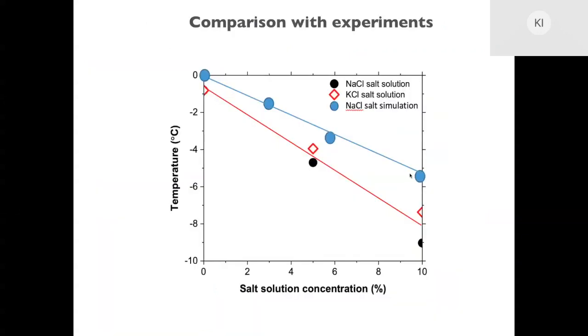The interesting thing here is that from the phase diagram of water, we can go and find the temperature that corresponds to the pressure that we computed on the small scales between the interface of cement and ice, and plot it as a function of the sodium concentration that we have. And here we see that we have a good comparison with experimental results that are shown in red and black. So that gives us an idea that we have a good estimate for the pressure where the material is freezing.